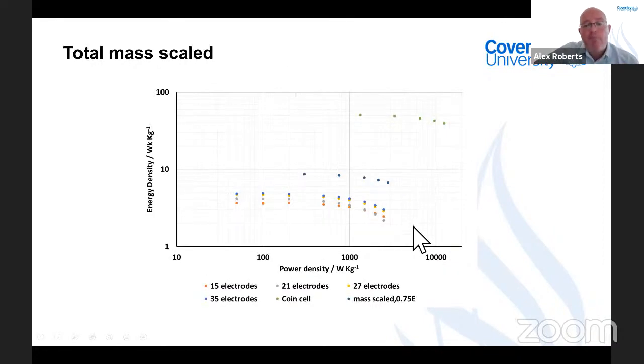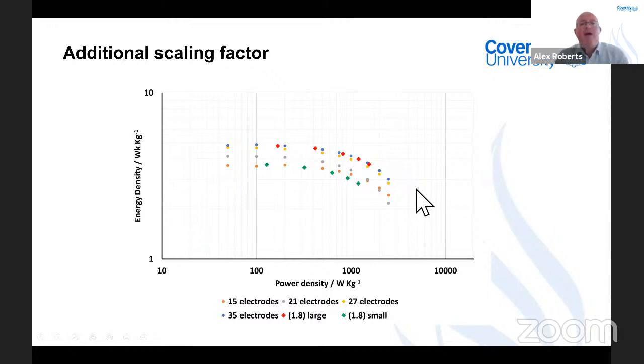And also I multiply my number by 0.75, because in the real devices we only cycle to half of the voltage limit, so we get 3/4 of the energy. And you can see it's this line in the middle here. Even by going through this scaling process, we still don't get the right values that we're looking for. We still don't match with what we get in the final devices. So we put this together and we can now add in an additional scaling factor, which is dependent on the cell format and the cell size. And you can see now, regardless of which electrode we use, we're now fitting in that area.